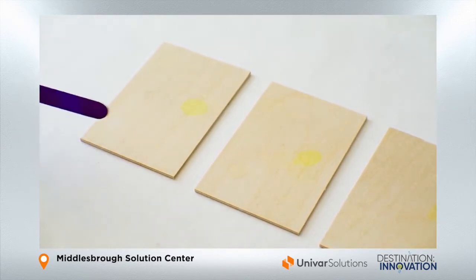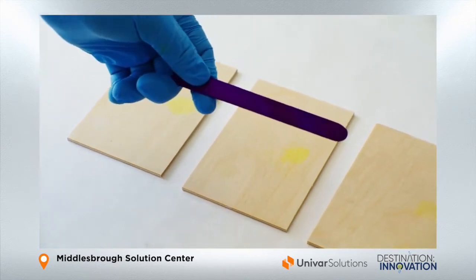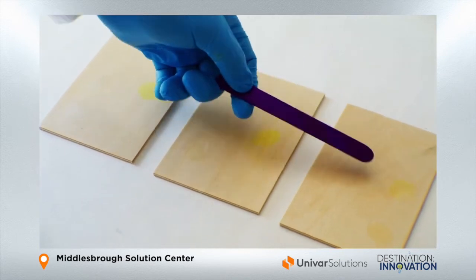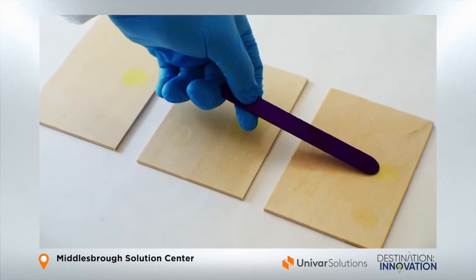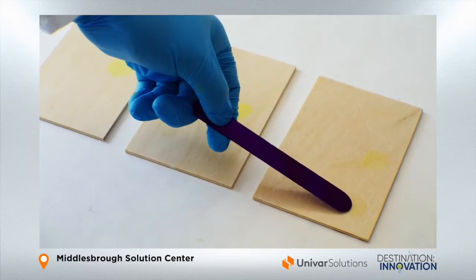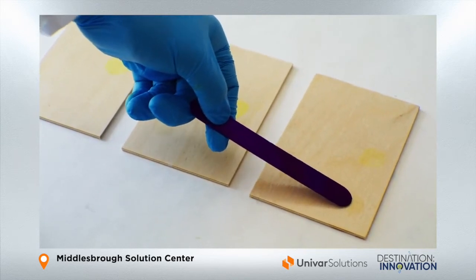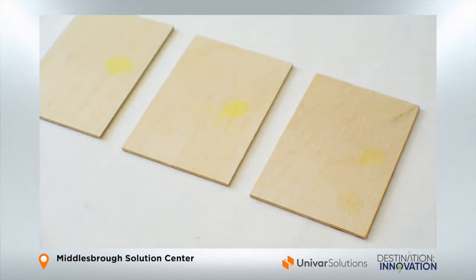And on the right, when you use the polyurethane acrylic hybrid, you see a lot less of a stain on probably the most severe one, which is the curry paste. But you also do see some marking from the coffee, which is only really apparent on the acrylic. So you do get the benefits. So when you're using this sort of thing, you have to get a balance. You may add some polyurethane to the acrylic resin, or you could also add a crosslinker. I can try and balance that out.